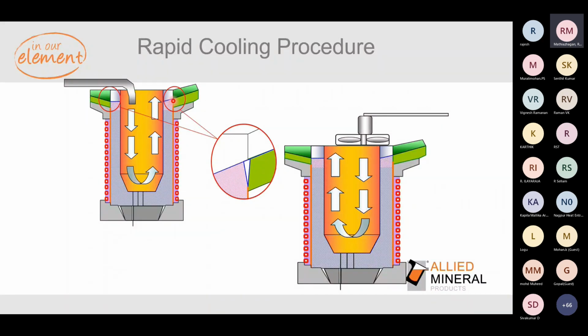So try to break those slags, so that actually the lining can settle down during the contraction with no hindrance. If the slag is going to be here, it is going to be tying up your working lining with the spout, and the lining will not contract smoothly. And because of that pressure, you can have any kind of horizontal cracks wherever the stress is created. So break those areas and then put a compressed air fan on one side. So air flows on one side and goes on the other side.